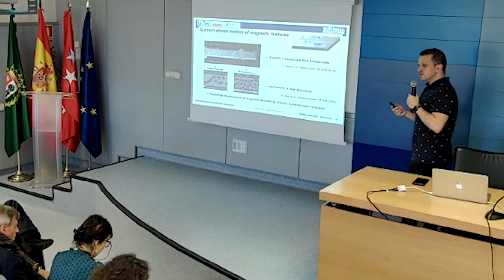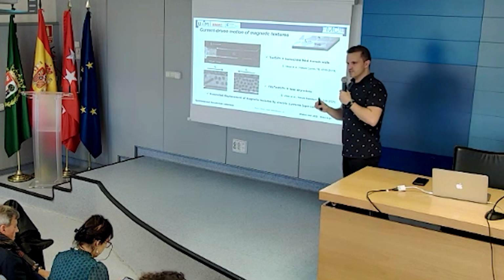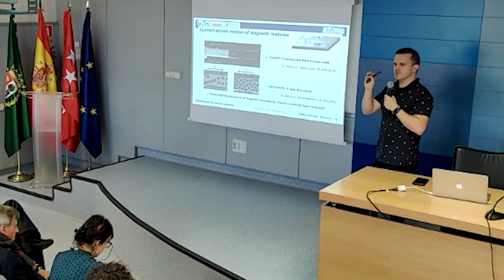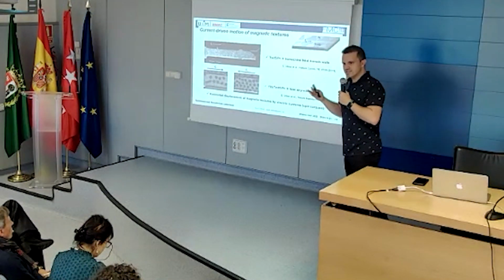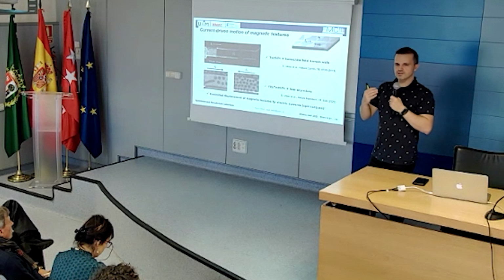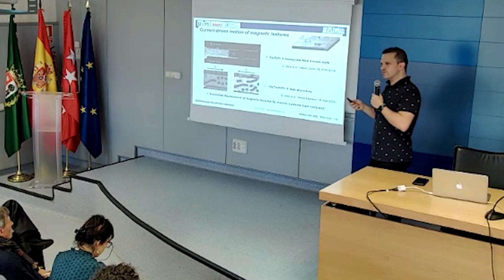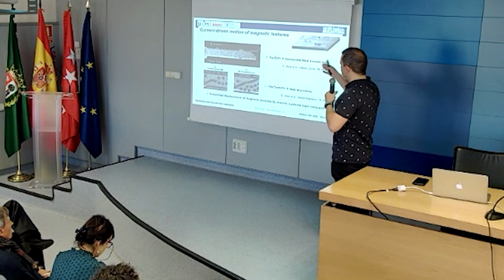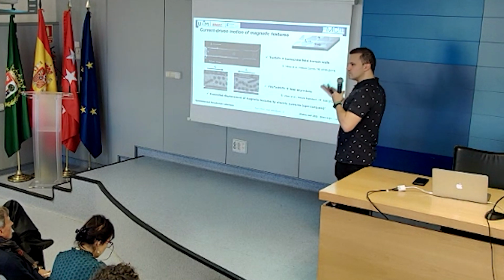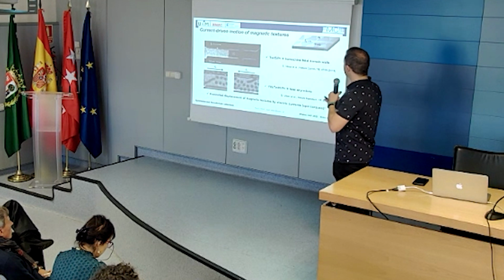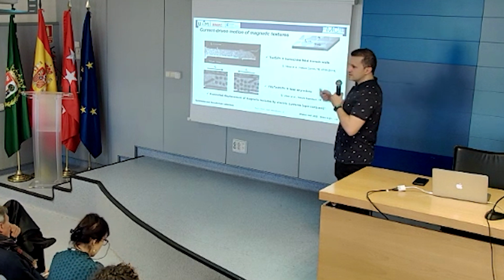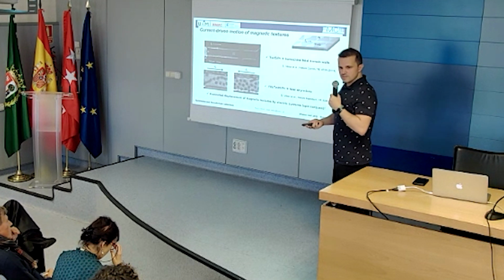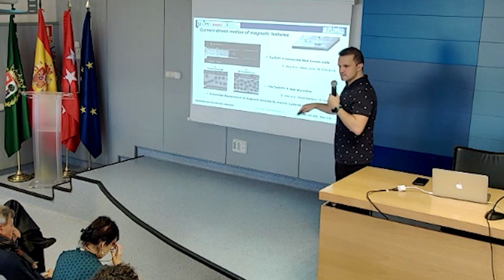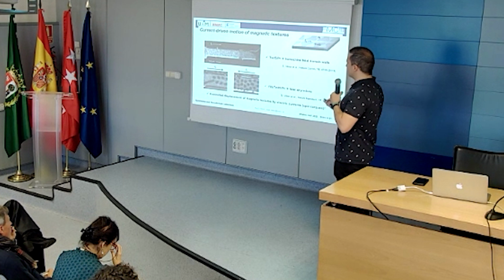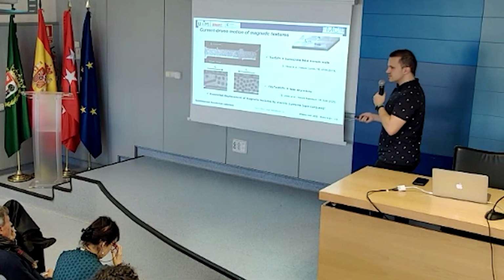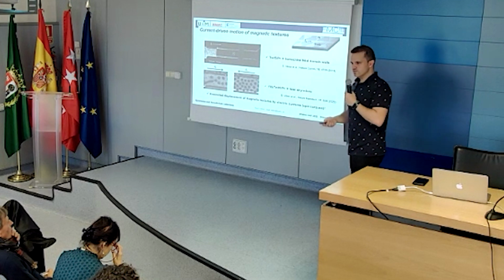That happens because of an interaction of these spin currents with the magnetic texture we have. We have to have a particular magnetic texture, because if we don't have what's called a Néel type domain wall, the coupling will not be correct. It will be Bloch type, there will be no coupling, and so on. The type of torques that you exert on the domain walls depends on where the polarization of the spin is pointing and which type of domain wall you have. The interesting thing is that this platinum layer, which helps you inject spins, brings the spin-orbit coupling to the system. And the spin-orbit coupling is what helps you stabilize this type of domain wall. So this stack is helping itself to get these domain walls that you want to drive.